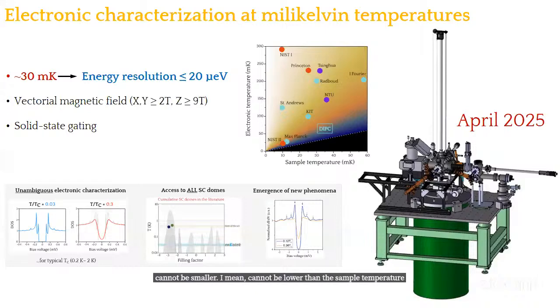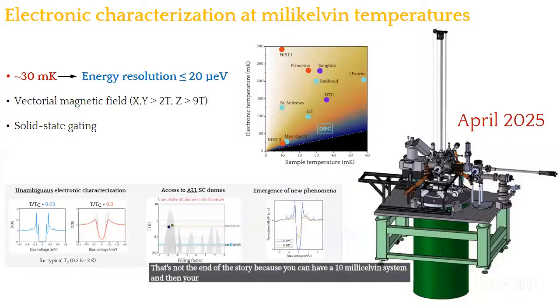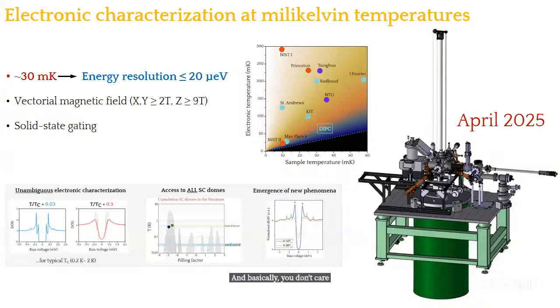So the idea, if you work in one of these millikelvin systems, is to work at a sample temperature as low as possible. But that's not the end of the story, because you can have a 10 millikelvin system, and then your electronic temperature, due to radio frequency noise, et cetera, can take you here. And basically, you don't care if you are working at 10 millikelvin if you have a noise that takes you here. Effectively, you are working at much larger temperatures. So what I'm plotting here is basically the declared ratios between the sample temperature and electronic temperature of the systems I'm aware of. But you can always train your system to avoid the electronic temperature problem. Yeah, that's extremely complicated.